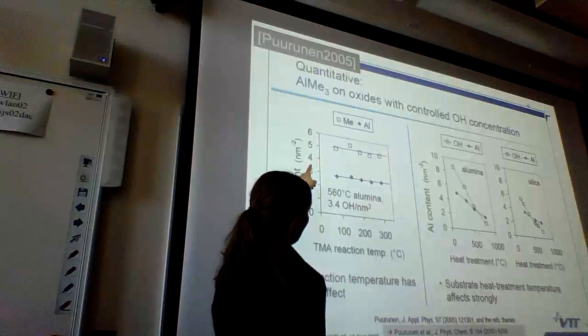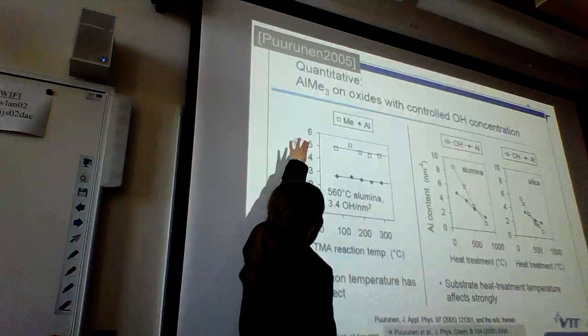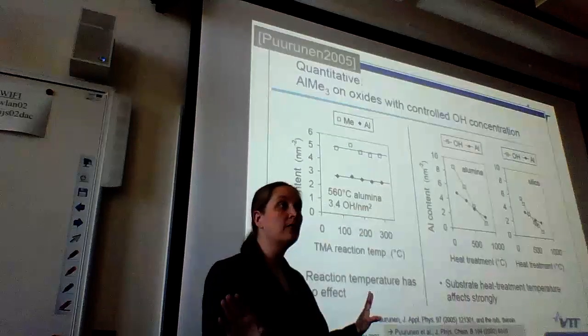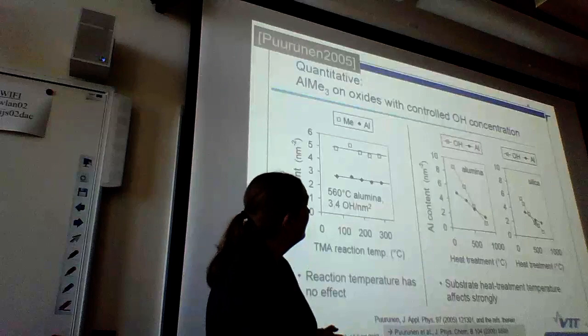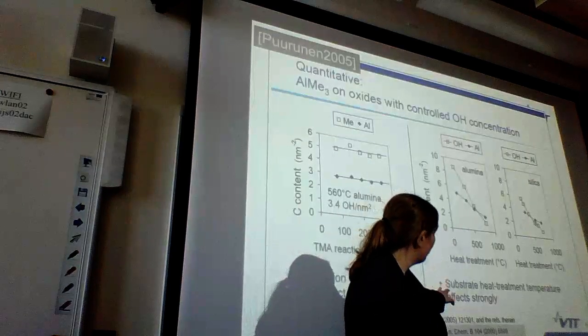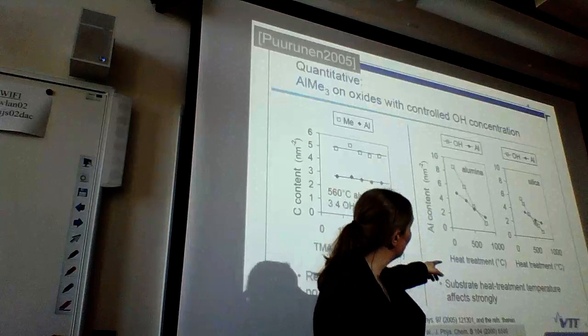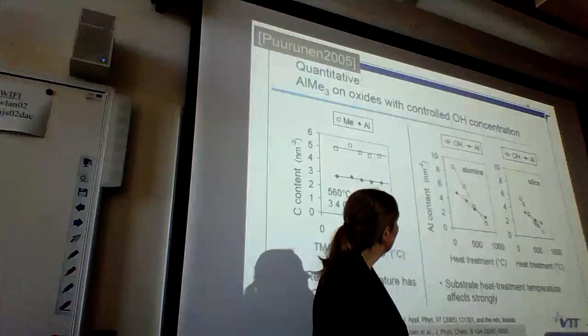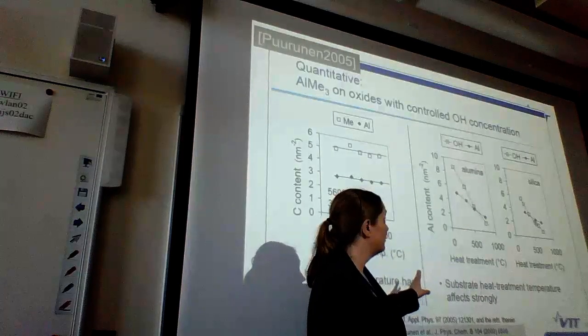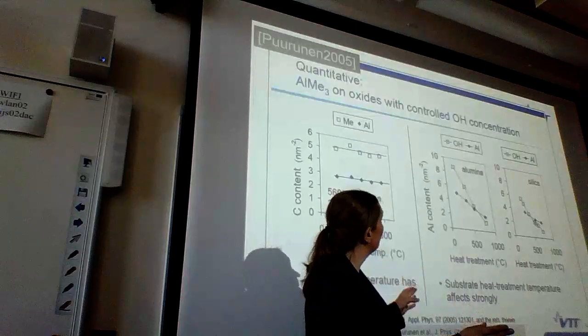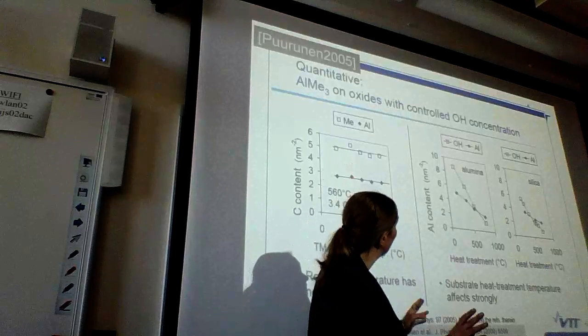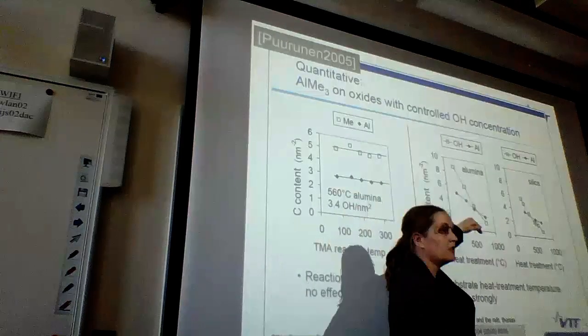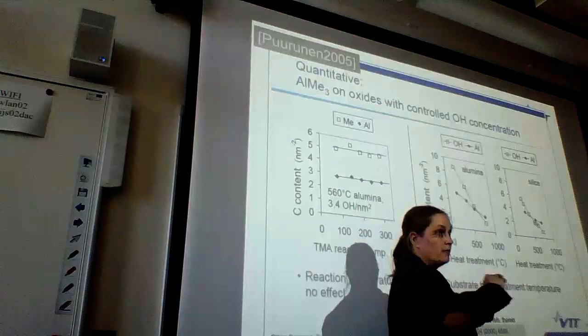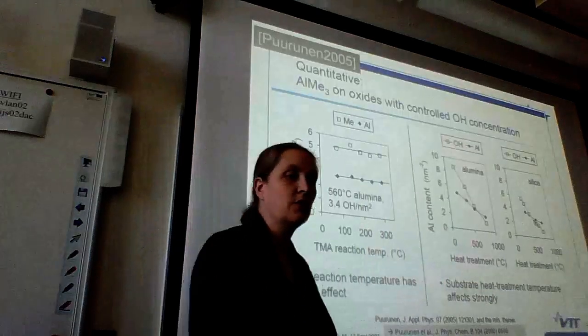You measure, well, this is alumina. The metal group content is measured, alumina is calculated from OH metal. But here you look at the metal group concentration. You have a flat line. So TMA reaction temperature has no influence. Then, varying the substrate heat treatment, giving a different OH group content, as seen with these unfilled symbols, and doing the reaction at the same temperature. Now separating the OH group content's influence from the reaction temperature, which influence we saw here, but anyway they can be separate. You see, they are changing in the same direction, but the slopes are different. So there is no one-to-one correlation. There is a correlation, but it's not a one-to-one correlation.